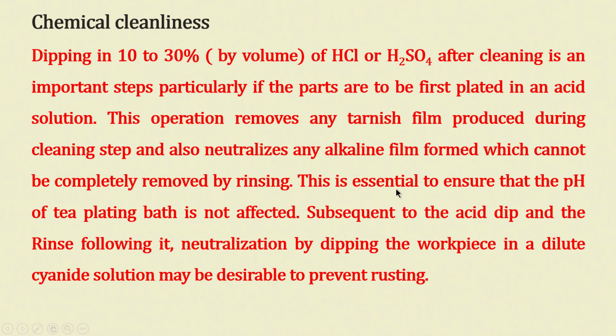So, this is essential to ensure that the electroplating bath is not affected. Subsequent to the acid dip and the rinse following it, neutralization by dipping the workpiece in dilute cyanide solution is also employed. If we want to plate with zinc or gold or anything, then a cyanide bath dip is also quite essential. So, quite often we employ that.